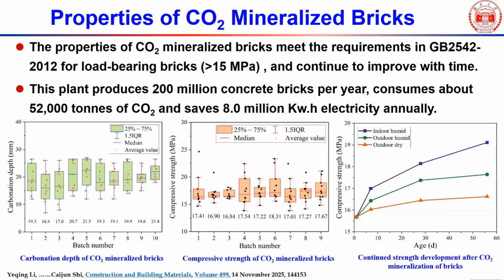Of course, during the past several years, we measured the carbonation depths. The thickness of the brick is 50 millimeters, so half is about 25 millimeters. You can see the majority of them reached about 20 millimeters on average. The strength is about 17 megapascal on average, and the Chinese standard requires a minimum of 15 megapascal.